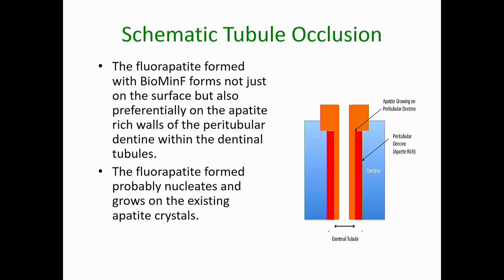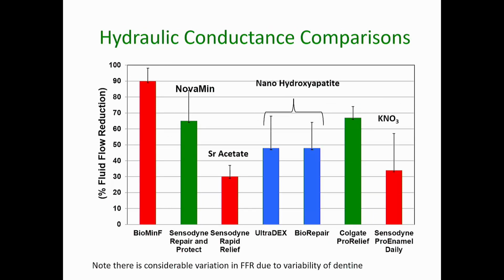We believe that the fluorapatite formed with the Biomin F forms not just on the surface, but preferentially on the apatite-rich walls of the peritubular dentine. In general, crystals like to form on a bit of the same or very similar crystal phase. And so the peritubular dentine, which is extremely apatite-rich, acts as a nucleating surface for the formation of more fluorapatite.